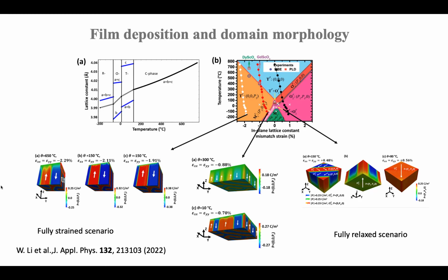But the good thing is, we know from the previous study that microstructure determines the local variation of the electro-optical tensor. And then we know that the thermal path will determine what you get. Actually, before I looked into electro-optics, there was always this controversy. Your barium titanate grown on silicon, is it in the compressive state or in the tensile? And there are reports of both. And I think it's because people cool at different rates. Essentially, if you want to follow this one or that one, it depends on how fast you cool.